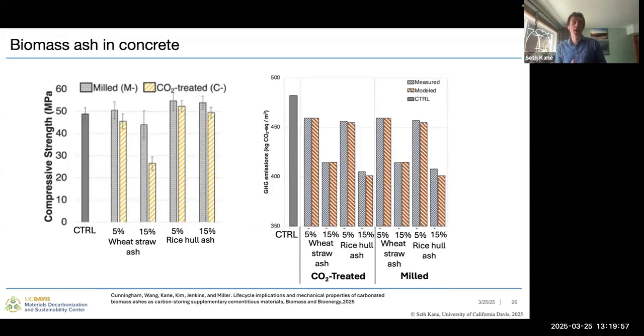Okay, so we then can take this ash and put it in concrete as a supplementary cementitious material, replacing that primary cement fraction of our concrete with either 5 or 15% of these ashes. And here we're just looking at a mortar control compared against a wheat straw ash and a rice hull ash at 5 or 15%. And those are being applied either with or without that CO2 treatment. And so we can see that in general, the rice hull ash is performing a little bit better than that wheat straw ash. That's a result of that higher silica content that we discussed earlier, and that can contribute to those pozzolanic reactions in there.